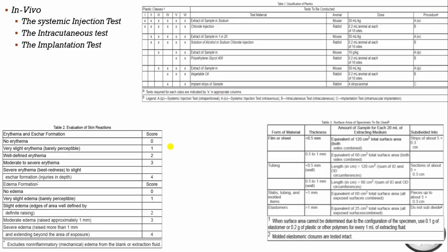In the implantation test, a sheet of plastic material is administered directly into the animal. Eight strips of sample and four strips of reference standard (high-density polyethylene, not less than 10×1 mm) are implanted into a rabbit with an average weight of 2.5 kg. After 120 hours, animals are observed for necrosis, discoloration, infection, or hemorrhage of surrounding tissue, scored on a scale of 0 to 4. The sample meets the requirement if the score does not exceed 1.